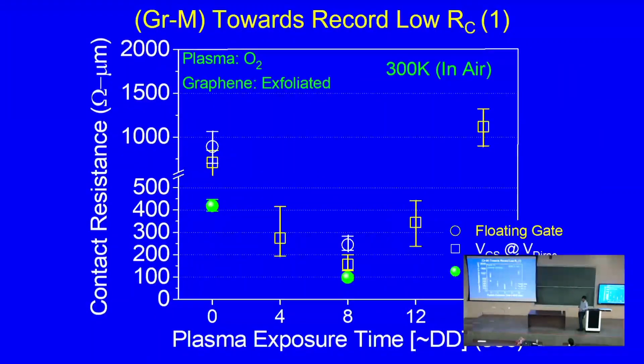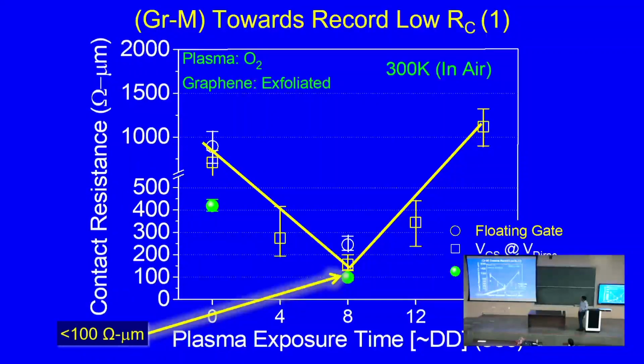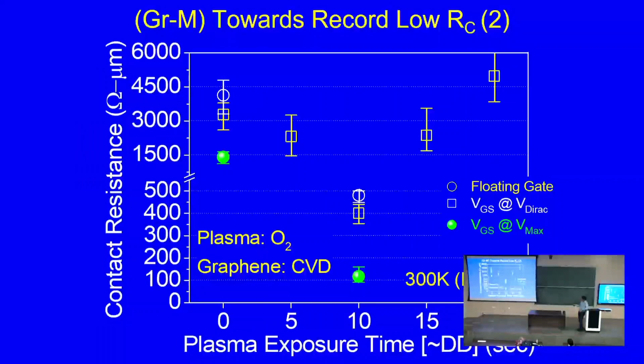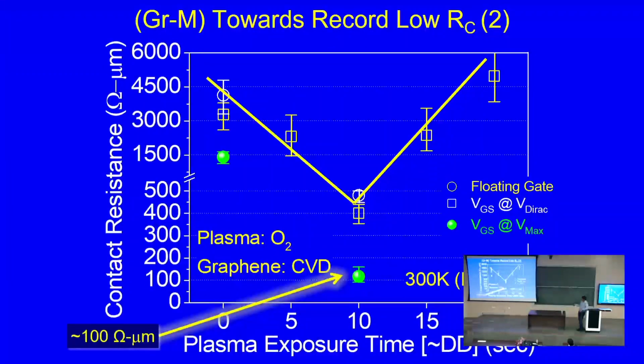Now coming to the contact data. This is all hard fact, all experimental data. What you see here is with oxygen plasma for exfoliated graphene, measured at room temperature in air, not 4 Kelvin, vacuum and all that stuff. This is exfoliated for benchmark, and as we increase the plasma exposure time, which means the defect density, you see an optimum. You see the contact resistance coming down to 100 ohm micrometer. The same we did for CVD. You see the contact resistance again coming down to 100 ohm micrometer, and when the contact resistance is optimum, the variability is also the least. All of this measured at 300 Kelvin in air.